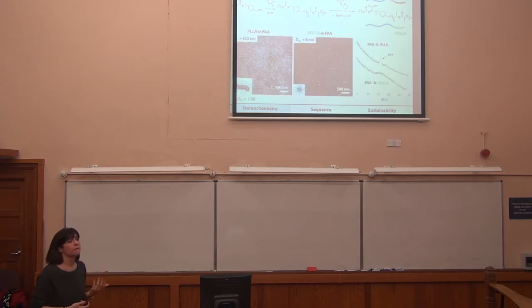To show how that affects the assembly of these molecules, this is a molecule we use quite a lot. It has a group that controls a radical polymerization and a group that controls a ring-opening polymerization, so it's just a difunctional small molecule. We ring-open lactide, either the L or the D, and then do a second polymerization through the other group, and we make essentially an amphiphile. It has a large hydrophilic portion and a very small hydrophobic portion. In that hydrophobic portion, one polymer has the L isomer, the other has racemic. If we take these polymers and assemble them, they form very different structures.